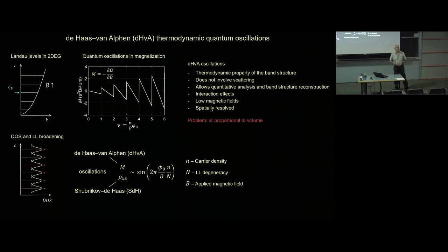So traditionally, de Haas-van Alphen has been used in metals and semiconductors to study band structures, but if you go from a millimeter three-dimensional sample to a micron-size, two-dimensional sample, you lose like 12 orders of magnitude. So obviously, the traditional methods for measuring de Haas-van Alphen are inapplicable to 2D systems. So the way we do it is, again, with our SQUID on tip.